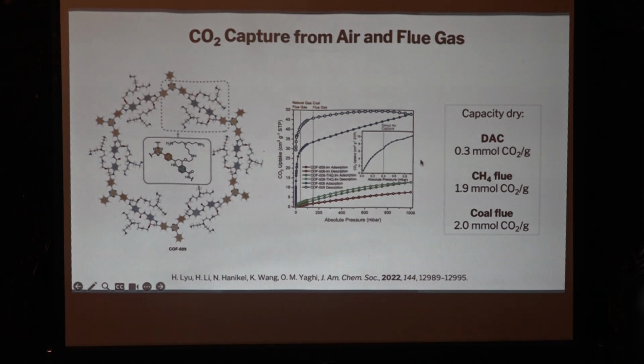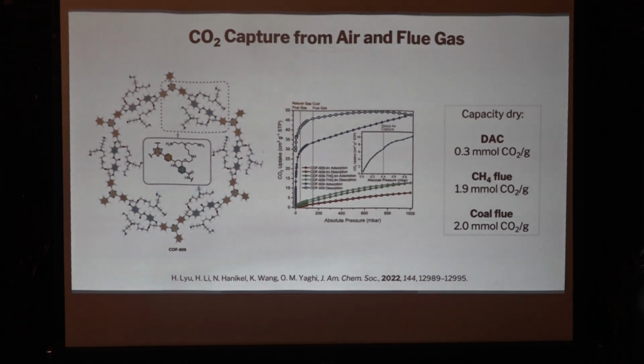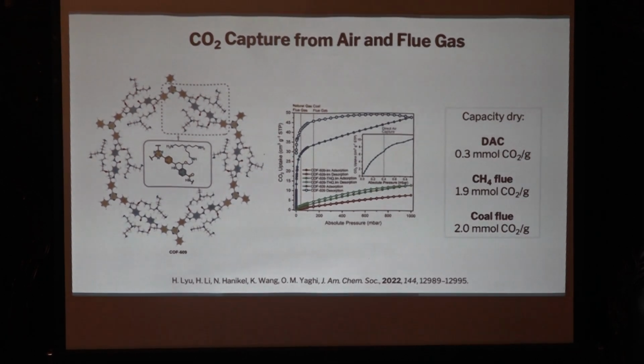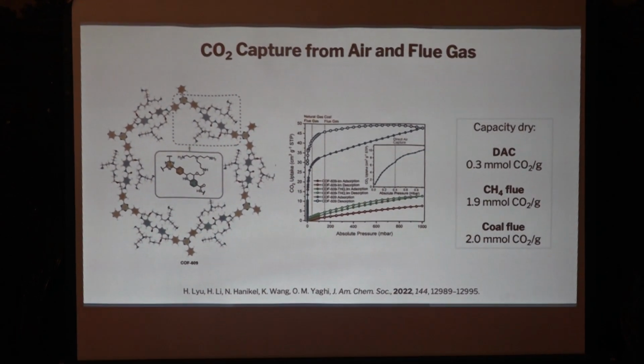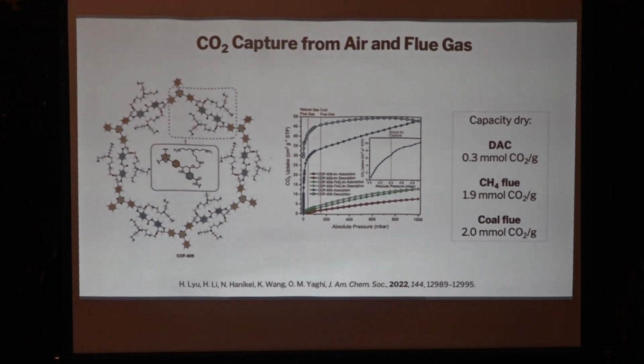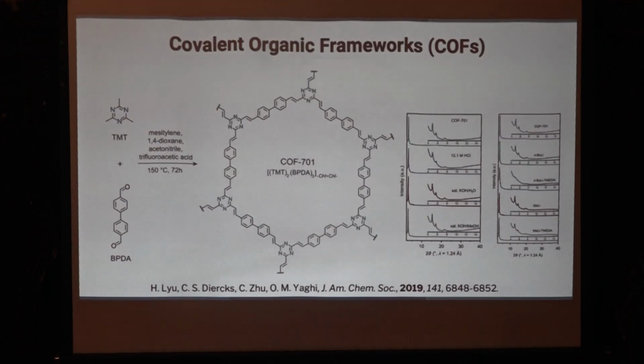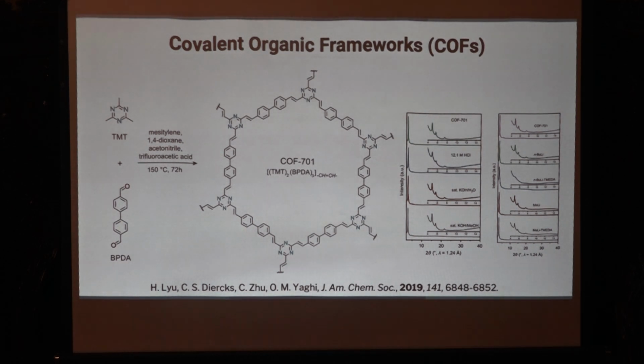How about cycling? Okay, so we have been cycling, not this particular material, but a new material we made based on this COF. And it's cycling now up to 100 cycles. No problem. I don't anticipate a problem. Why would a material that has a backbone like this be destroyed? I already showed you that it's stable in all these conditions. So we think we have the answer to the CO2 problem.